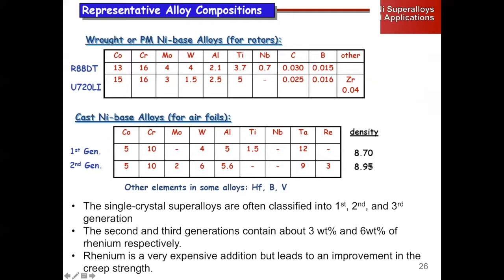There's also another disconcerting trend: as we improve our compositions, they tend to get heavier because we're adding more and more heavy rare earth and refractory elements to them, right? So we're going the opposite trend than we really want to go. We really want to go lighter, right? Because we have to fly this thing. But the fuel savings from lighter components are markedly offset by the higher temperatures you can go to. Thermodynamically, if we can increase the operating temperature, we get a lot more bang from our buck than we can by reducing the weight of these engine components.